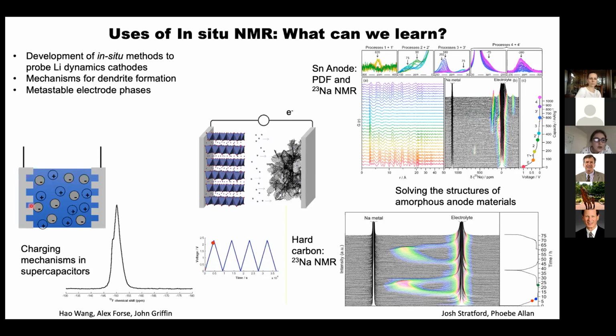And then when you charge them, you store charge by forming a double layer or intercalation of ions inside the pores. And what we were able to do was use, in this case, fluorine NMR to look at the BF4 minus, to actually look at the ions going inside the pores and to quantify how many ions went in and what the charging mechanism therefore was in these different types of activated carbons.